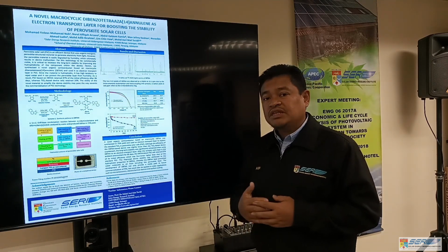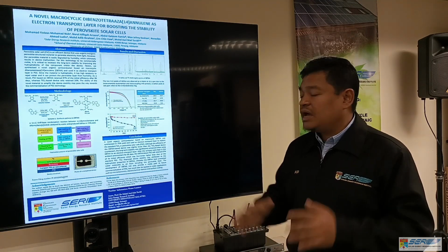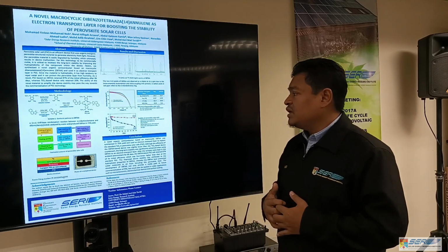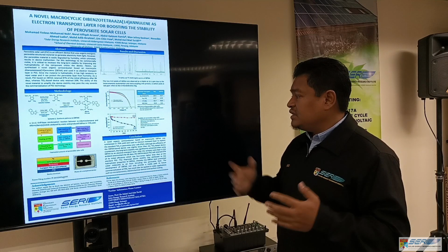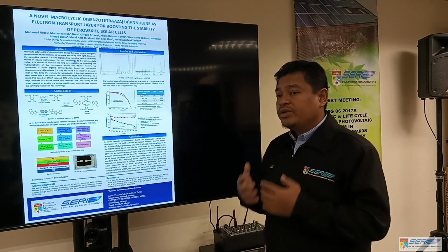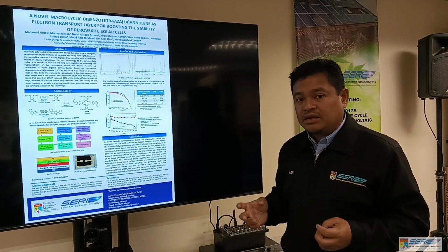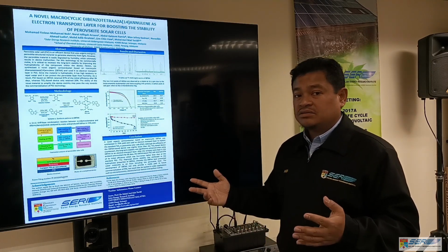We go for the stability. After we measured the stability up to 3 months, what did we achieve? For normal TiO2, the performance reduces by about 80%, so only 20% is still working for the device.